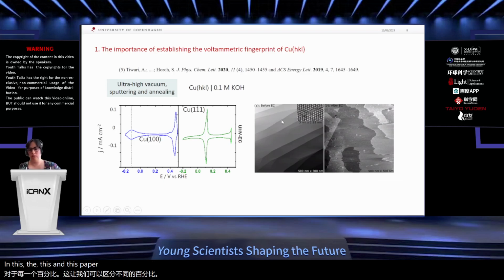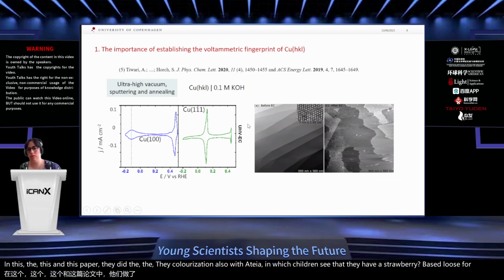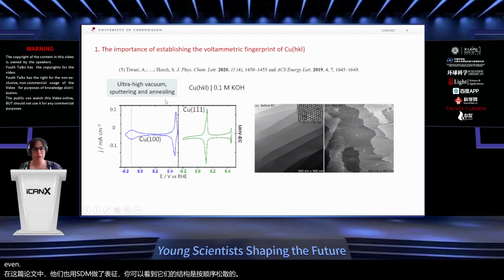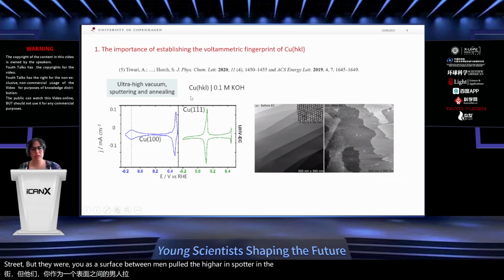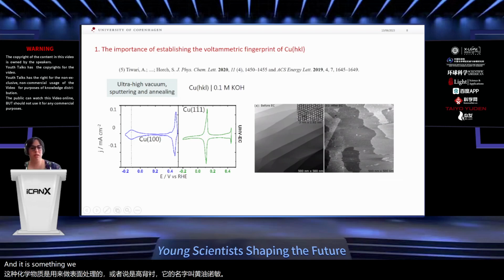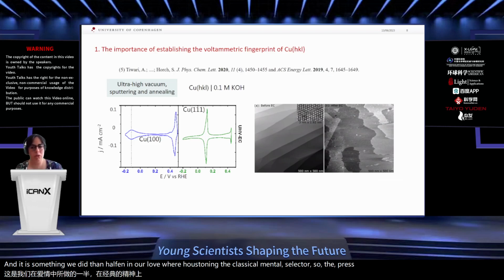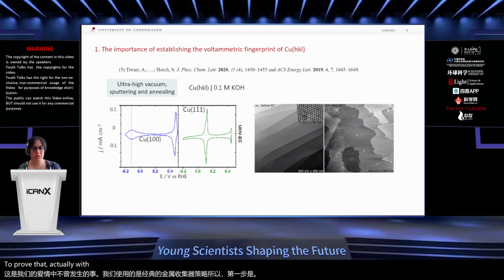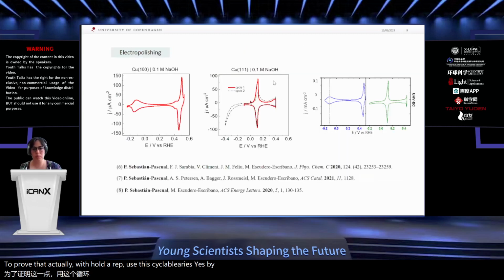In this paper, they did the characterization also with STM, in which you can see that they have a surface that looks quite ordered even after electrochemistry. But they were using as a surface pretreatment ultra high vacuum techniques, sputtering and annealing. And this is something we didn't have in our lab. We were using the classical method of electropolishing. So the first step was to prove that we could actually reproduce these cyclic voltammograms just by using electropolishing.